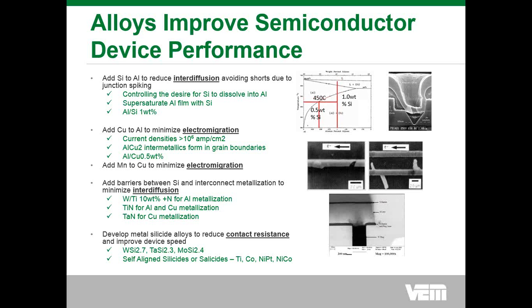And then as the technology has progressed, what we find is the current densities, the amount of electrons going down a circuit path, becomes ever increasingly higher. Today, well above 10 to the 6 amps per square centimeter. When you're flowing that much electricity down a very fine conductor, not only do the electrons flow, but you get a net flow of the atoms in that line, leading to the problem of electromigration. To solve this problem, the semiconductor industry developed the aluminum copper alloys. And what they're making use of is the fact that aluminum copper will form metallic compounds in grain boundaries, minimizing the ability for the aluminum in that trace to actually migrate.